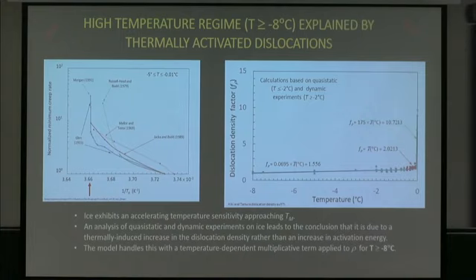But what I was able to find by analyzing my results up to about -3, and then these results by Heike and Tamura from '81, they actually did some pulse echo measurements and got dislocation densities right up to the same temperature of the Morgan data, -0.01. And what they saw was this kind of piecewise linear increase, just exactly what Morgan saw. And as I say, my data didn't quite go up that far, but I got this same trend in here at lower temperatures. And it gives you about an order of magnitude jump over the last couple tenths of a degree in dislocation density. That's exactly what's needed to explain the increase in creep rate with temperature up to -0.01. It was right on the money.